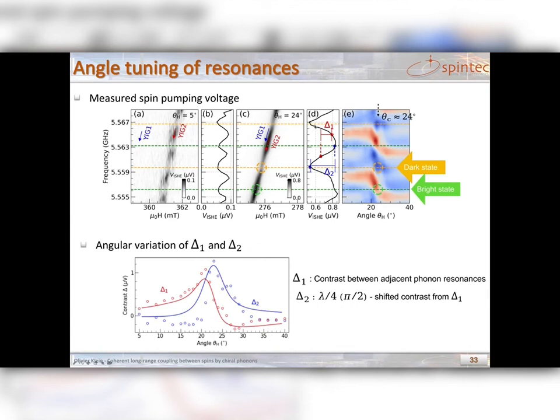Here is represented the full angular dependence of this contrast, which shows this formation of bright and dark states. Also, the contrast inverts after the crossing, which is normal because you have acquired a phase shift of 180 degrees. It's also quite useful to define a contrast. Here, delta 1 is the contrast between phonon lines, and delta 2 is the contrast when you have shifted by a quarter wavelength. When you plot this as a function of angle, you see that delta 2 has a resonance-like shape, while delta 1 is like a 90-degree shifted dispersive shape.